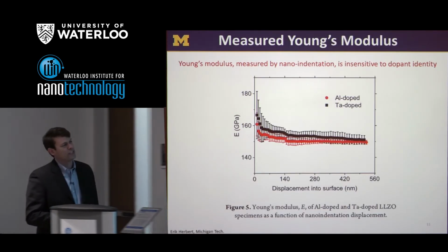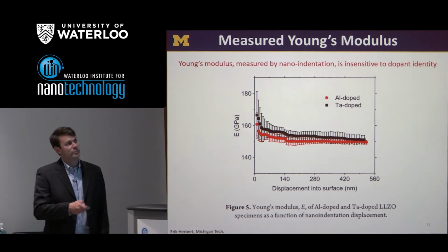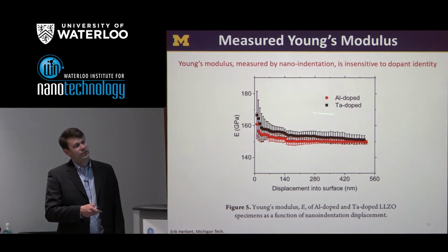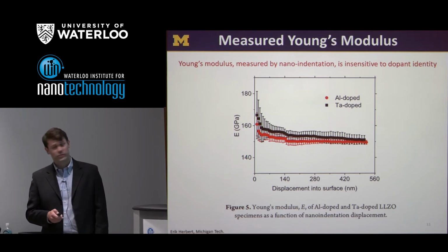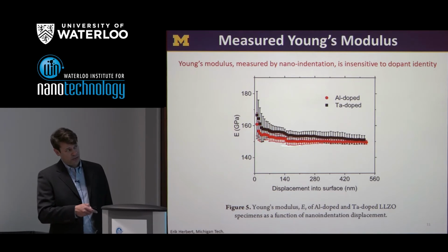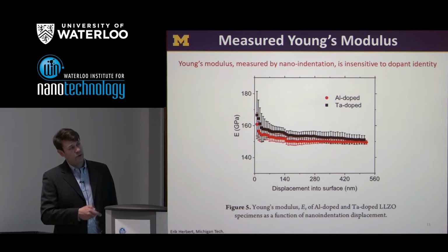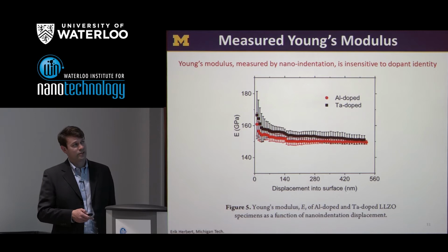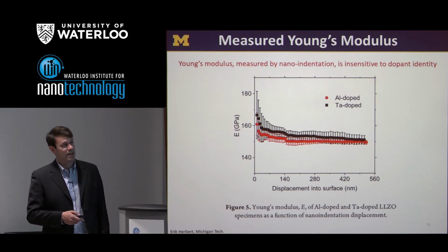So Eric Herbert at Michigan Tech took one of these samples and did some nanoindentation. In this case, looking at both of those compositions, and so what's plotted here is the Young's modulus as a function of displacement of the nanoindenter into the surface. And as you can see, once you get beyond a surface region, both of these compositions have roughly the same value of about 150 gigapascals.